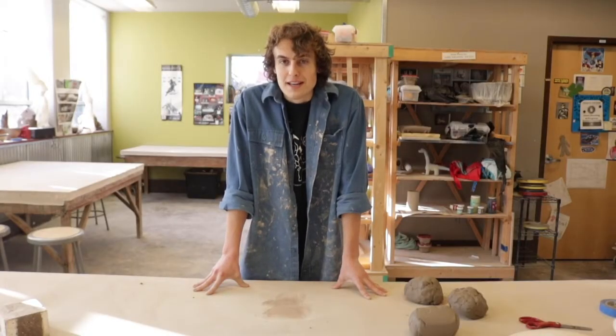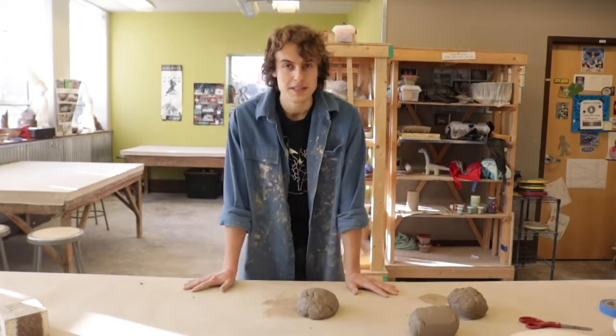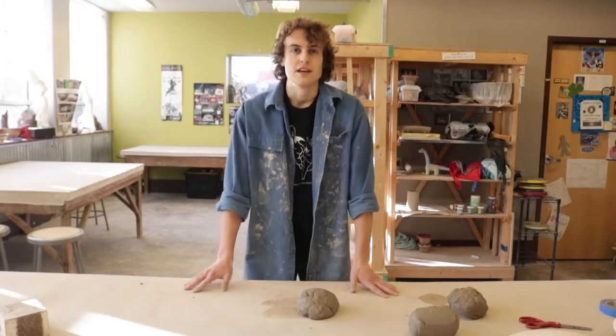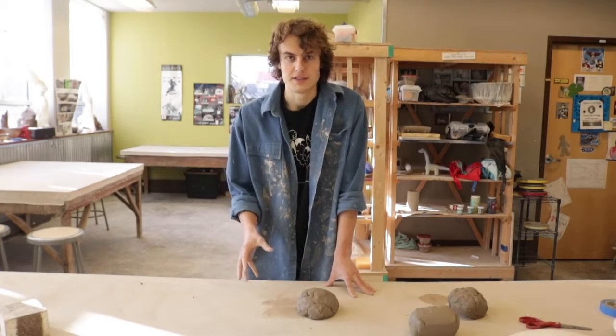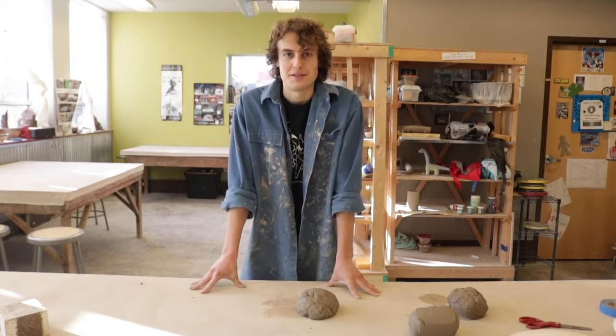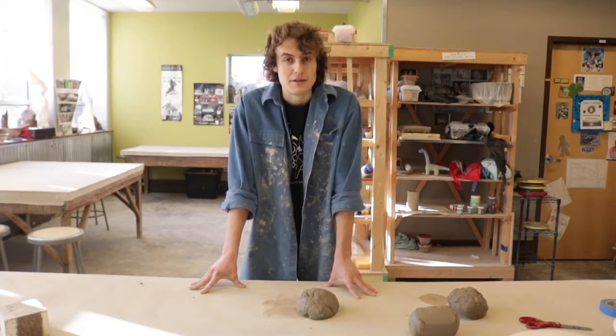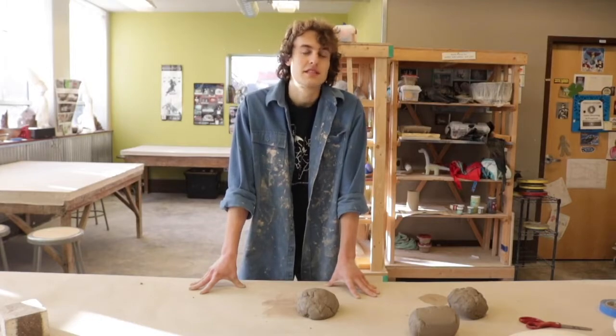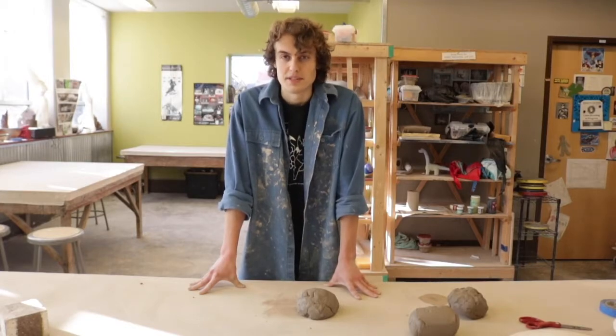Now that we got vocabulary out of the way, let's get into some demo — the fun stuff. First up is wedging. According to Professor Benson, wedging is the first most important process of making anything out of clay, whether it's hand-built or wheel-thrown. Wedging is the process of removing air bubbles from your clay and homogenizing it, which increases the structural integrity of your vessel. Air bubbles in your vessel can hold moisture, which can lead to explosions in the kiln when it's being fired. Not only will this obliterate your piece, but it'll probably obliterate the pieces around it too. Throughout human history, we've come up with many different ways to wedge clay, but all you need to worry about for this course is the boar's head technique.